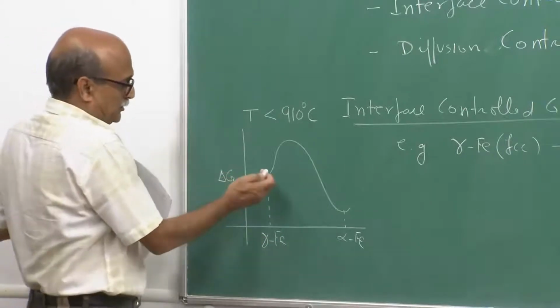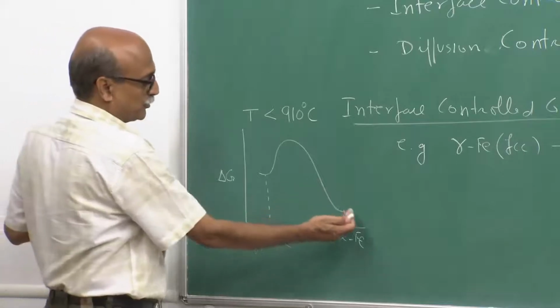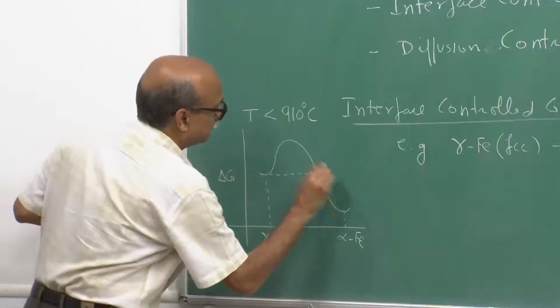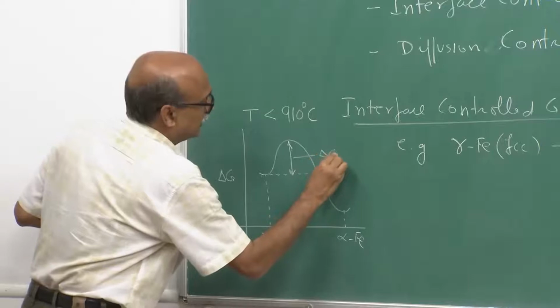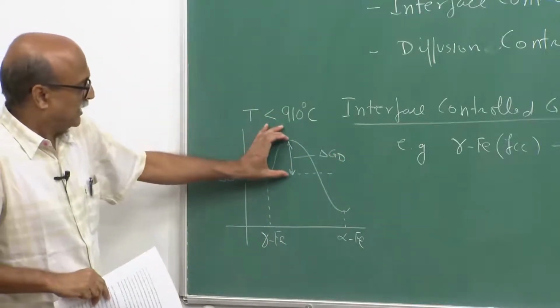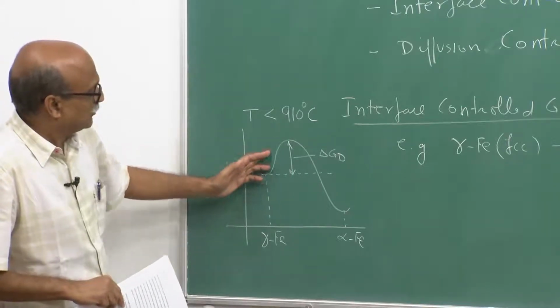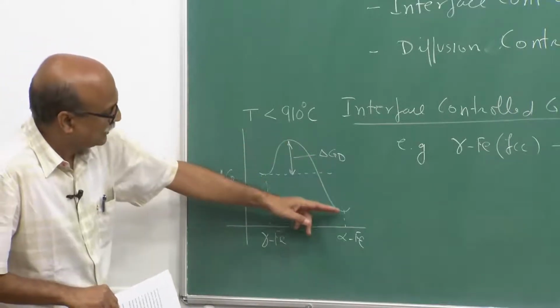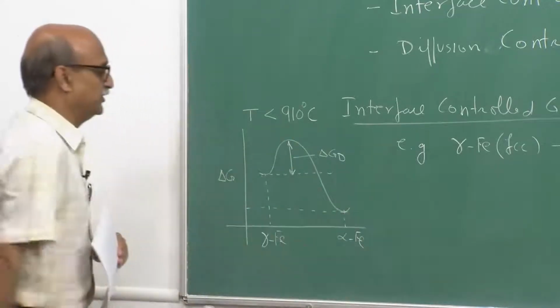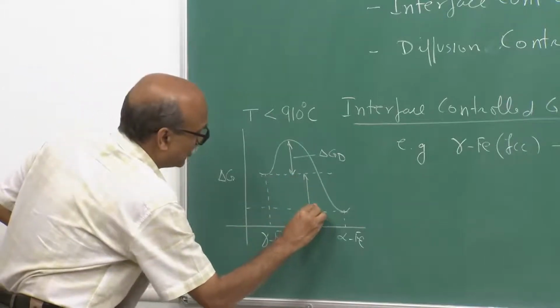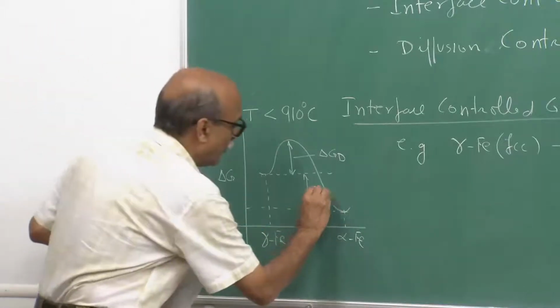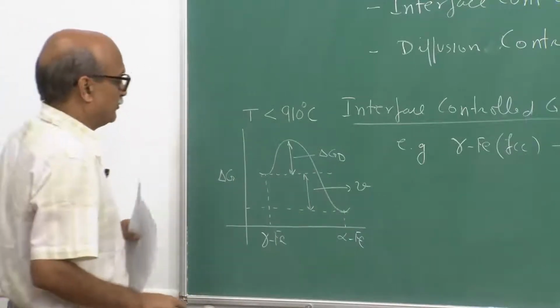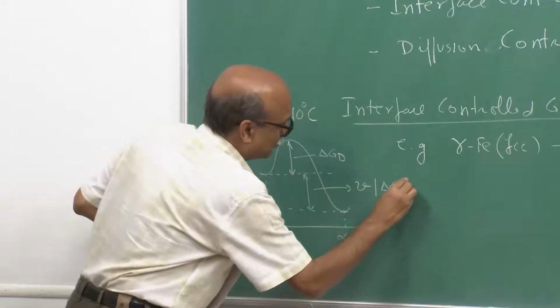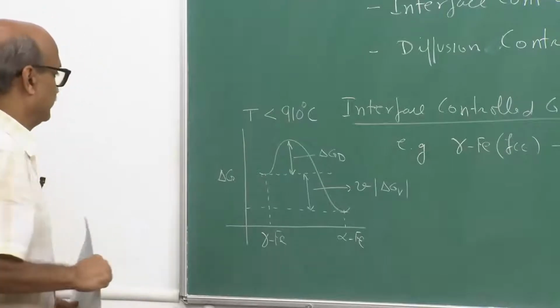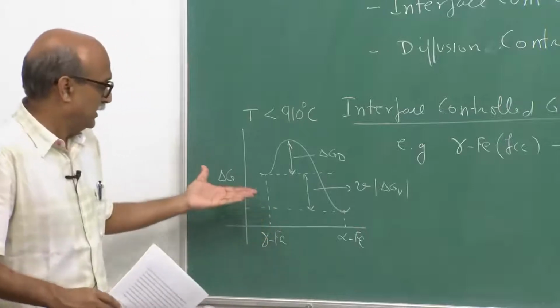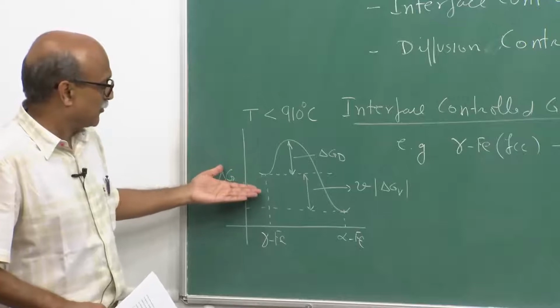So, what is the barrier to jump for an atom from the parent gamma phase to the product alpha phase? This barrier is what we have called delta GD. So, this is the energy hill that is involved for an iron atom to jump over this barrier, and beyond this it will simply go down to a much lower energy level. And what is the difference between the energy level of gamma iron and alpha iron? That is simply, we already know, the volume of the product phase multiplied by the absolute value of the volume free energy change. So, hence clearly the thermodynamics favors the jumping of atoms from gamma to alpha.